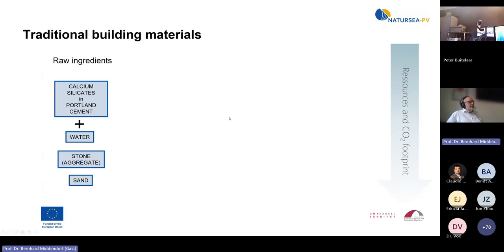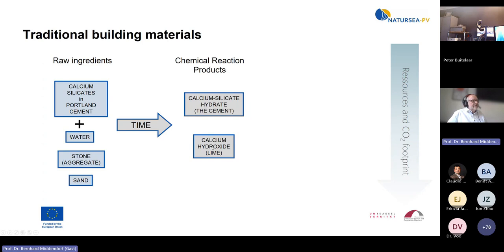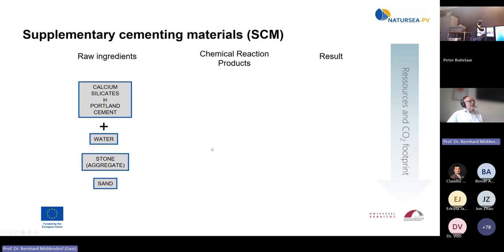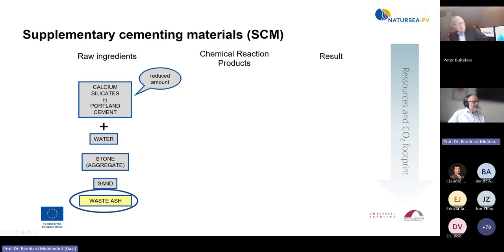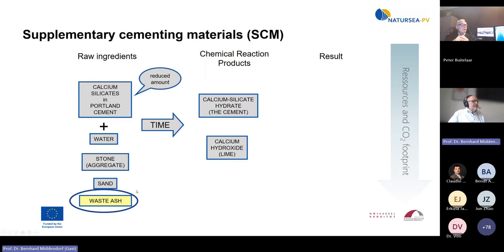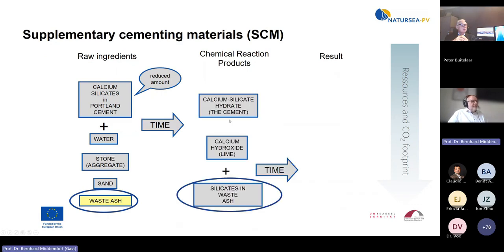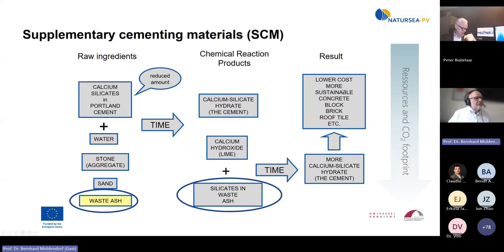So that means when you look at a traditional building material like cement, you have the calcium silicates in the Portland cement plus water plus your aggregate. And then over time you have chemical reactions, you get the CSH phases and calcium hydroxide, and the result is your concrete block. When we now supplement the Portland cement, that means we reduce this part and add some reactive wastes. I don't like the word waste, so recycled materials, active materials. Over time we have the same reaction products, but we also have some silicates in the waste ashes. We get more calcium silicate hydrate in the cement, but we have lower costs and more sustainable concrete.